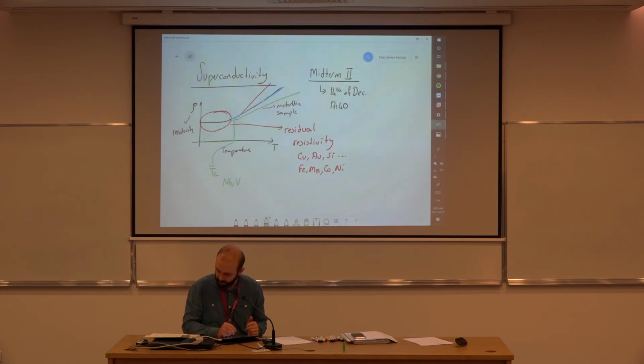So in some other metals, the easiest one is niobium. Then vanadium shows superconductivity. Actually, pretty much half of the periodic table shows superconductivity. Some metals at much lower temperatures, like the typical TCs are like for niobium, it's about 9.5 Kelvin. For vanadium, it's 5.38 Kelvin. And there are some others like molybdenum. It's 0.92 Kelvin. Yes? It's completely 0. Not even like a tiny amount. It's completely 0.